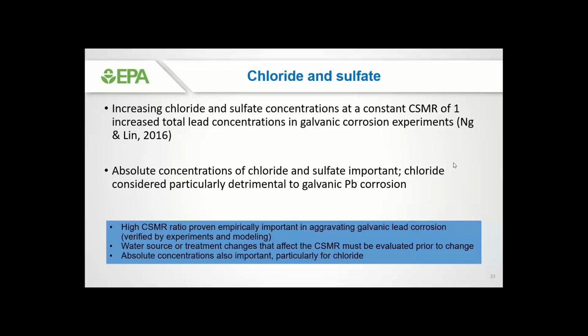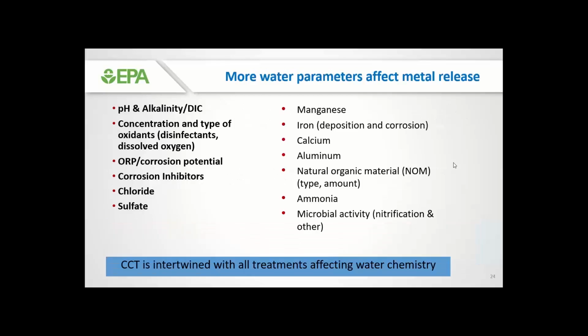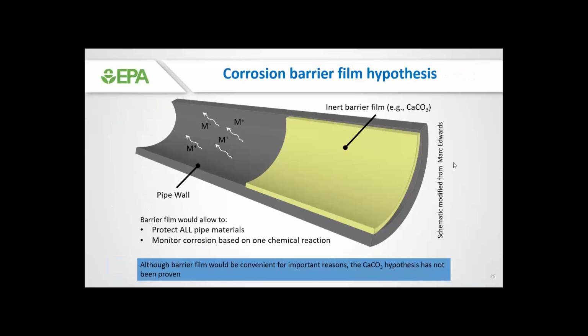So any water change that affects this ratio, any water treatment change, a coagulation change, for example, changing chemical, must be evaluated. But the absolute concentrations of chloride and sulfate individually are also important, particularly in the case of chloride, which is a very aggressive ion for lead, copper, iron, and metal corrosion in general. There are a lot of parameters that affect metal release, aside from the ones that I've had time for. So please keep in mind that corrosion control treatment is intertwined with all of these other things that affect water chemistry and the makeup of scales, such as manganese, iron, calcium, and others that I mentioned earlier.